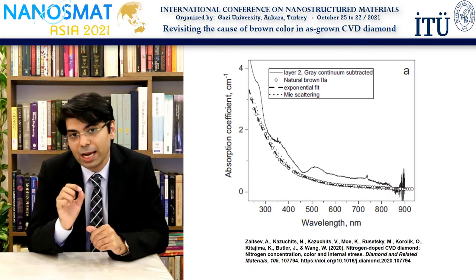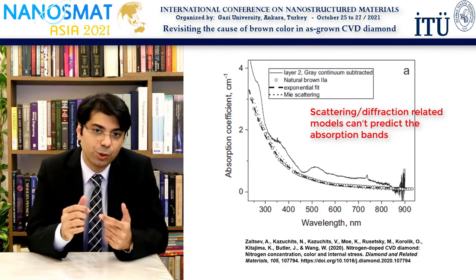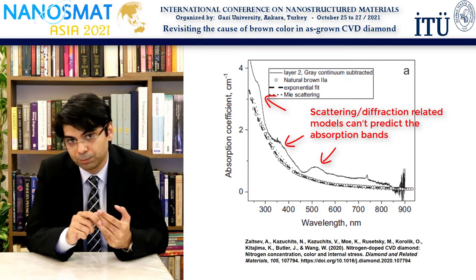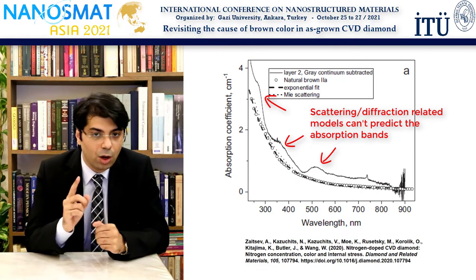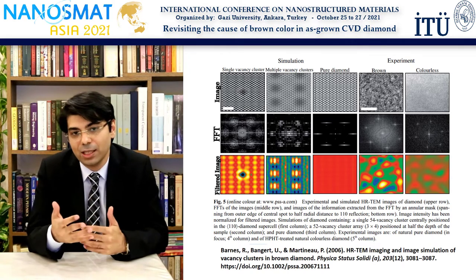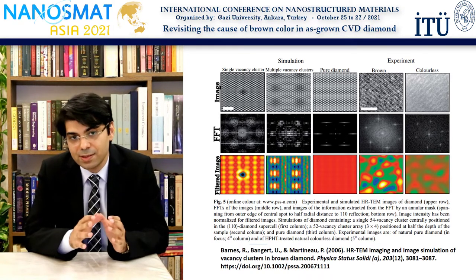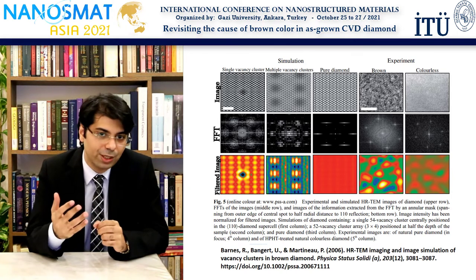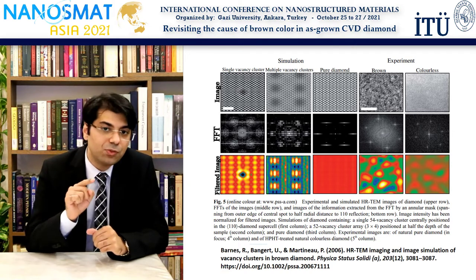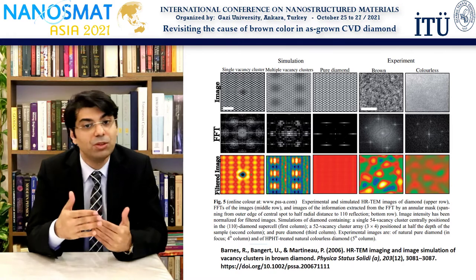However, such diffraction-related models fail to predict the experimentally observed bands at 270, 350, and 510 nm. There is also an interesting observation that vacancy clusters can be seen under transmission electron microscopes. However, such studies have not been conducted on a statistically significant number of samples, and the cause and effect between the brown color and the vacancy cluster, even if they exist, has not been very well established.